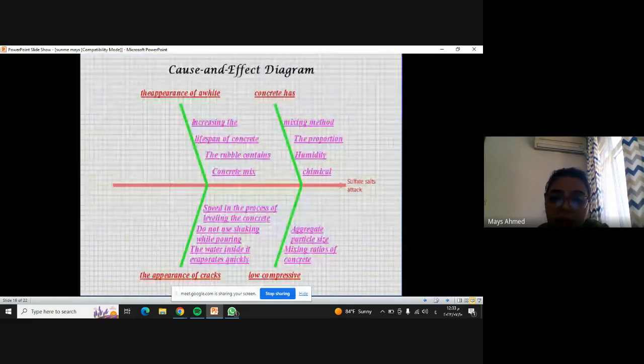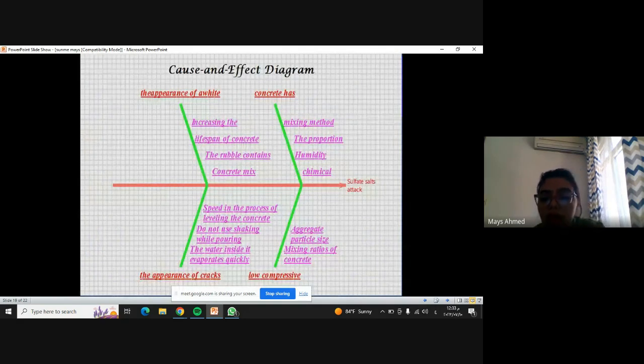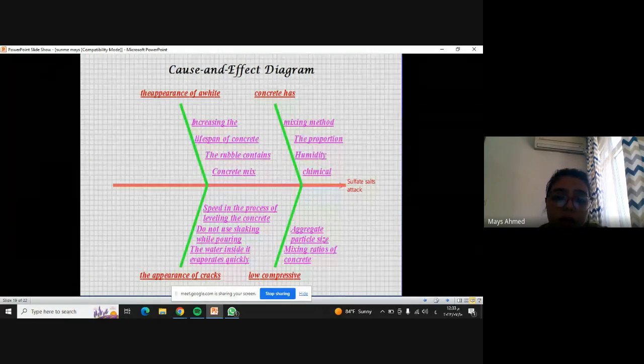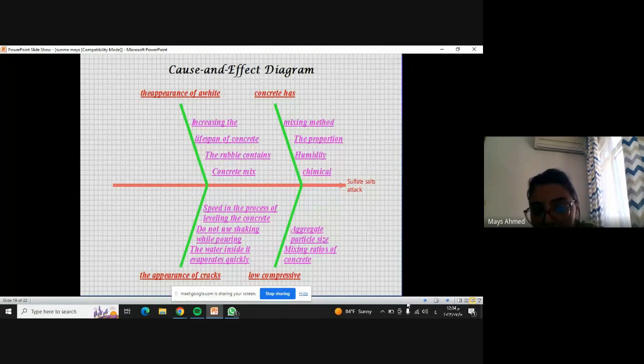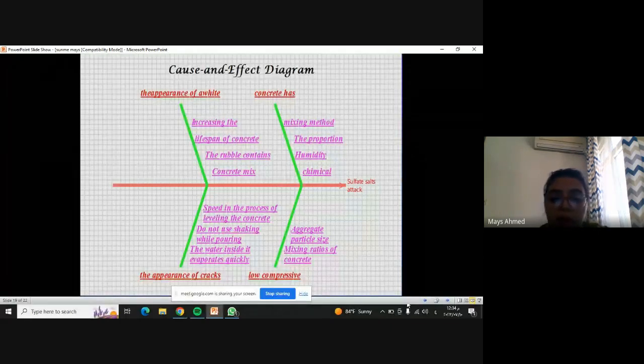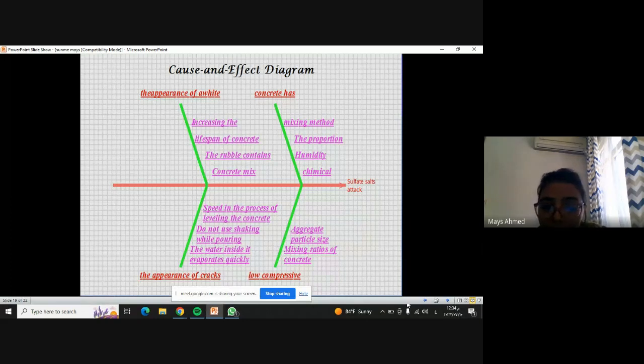Now we discuss the cause and effect diagram. We have concrete with low compressive strength, and we have the appearance of white deposits and the appearance of cracks. The concrete has low compressive strength. We have the mixing method, the proportion, humidity, chemical, and in the appearance of white, we have the lifespan of concrete, the rubble concrete mix. When the sulfate salt attacks, we have aggregate particle size, mixed ratio of concrete, and we have speed in the process of curing. This is so important. Speed in the process of curing the concrete. Do not use shaking. When pouring, the water inside it evaporates quickly.